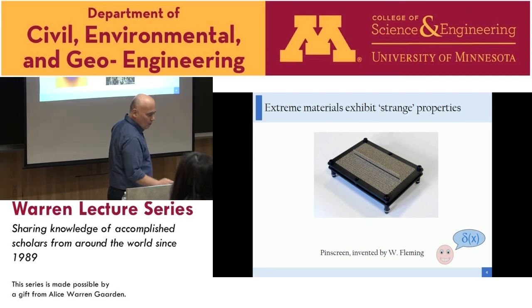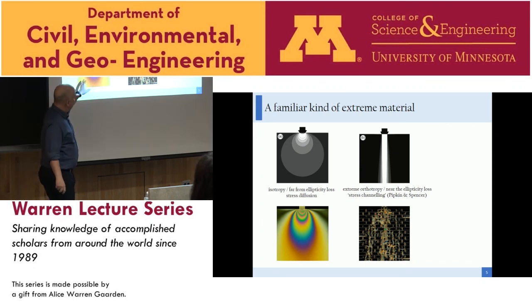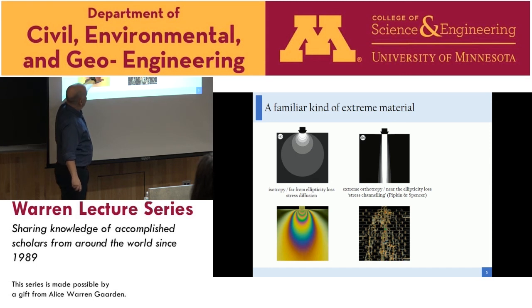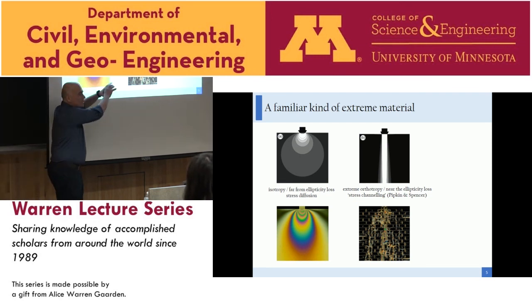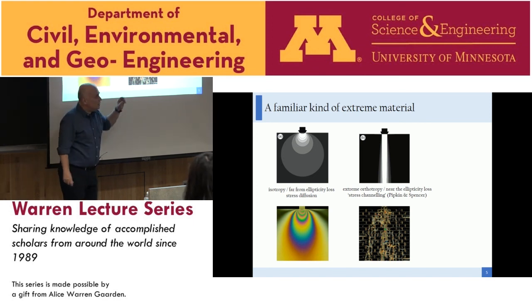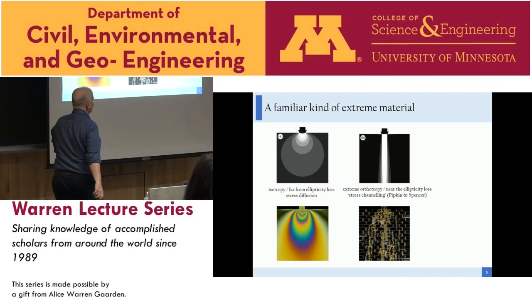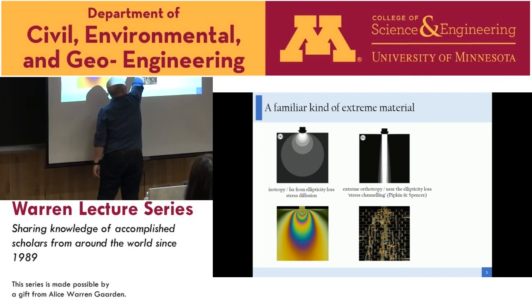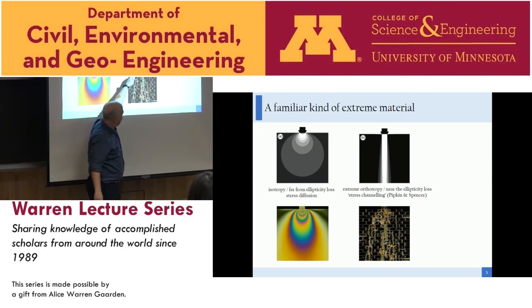Here we have two more engineering examples. On the left is an intact elastic plate loaded with a vertical load — a photoelastic test showing the contours of in-plane deviatoric principal stress, and we see the stress diffuses inside the body. On the right is the same setup made of small photoelastic bricks, and we see the stress percolates nearly vertically — completely different behavior.